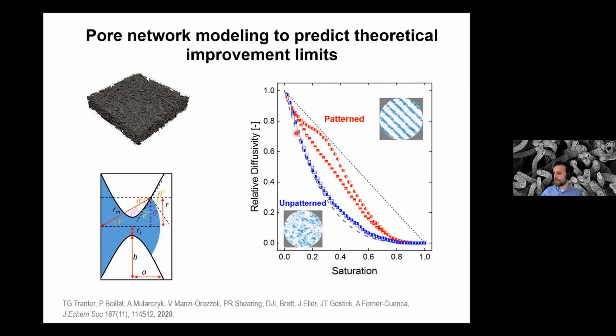And what you can see in these simulations is that when you compare an unpatterned material, so a baseline with a pattern, GDE, you can see that you gain at a saturation of 0.2 or so, you gain about double effective diffusivity, and that translates in electrochemical performance. So it does make physical sense to go from unstructured wettability materials to materials with pattern wettability. And modeling, so three-dimensional modeling, can help you inform the development of materials. But the final effort was, of course, to put these samples into a fuel cell and measure the electrochemical performance.